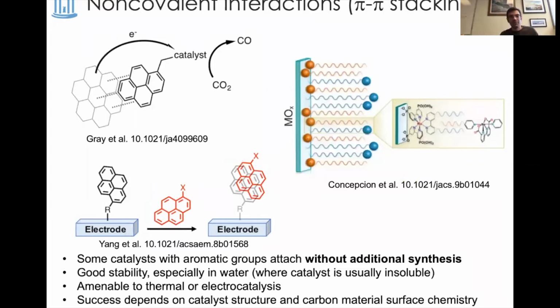Okay, I think the last of the catalyst modifications that I'll introduce is those involving non-covalent interactions, most commonly with pi-pi stacking interactions. And the irony in having this at the end of this section is that this is maybe the only case where there are some catalysts that need no modification at all to undergo a non-covalent interaction with an electrode. So some catalysts like porphyrins or phthalocyanins have aromatic ligands that will form pi stacking interactions with carbon electrodes spontaneously. Other times you need to install an aromatic group like a pyrene at the periphery of a catalyst to engage in these non-covalent interactions.